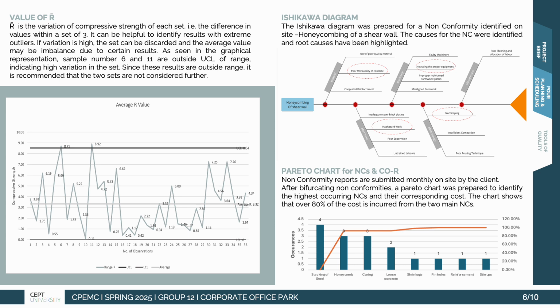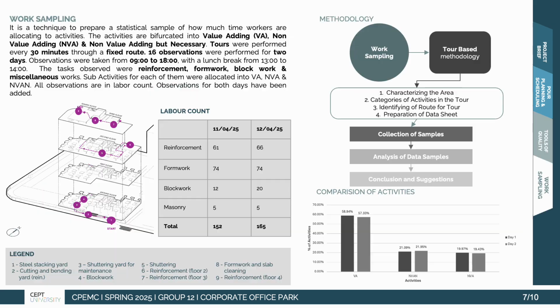A Pareto chart was prepared for the non-conformities and cost of rework. So non-conformity reports are submitted on a monthly basis by the client to the contractor. And after bifurcating all the non-conformities through 6 months of NC reports, a Pareto chart was prepared to identify the highest occurring non-conformities and their corresponding cost. So as seen in the chart, the top two non-conformities are mainly honeycombing and stacking of steel, and the cost for rework is mainly in honeycombing. So it shows that over 80% of the cost incurred is due to the main non-conformities.